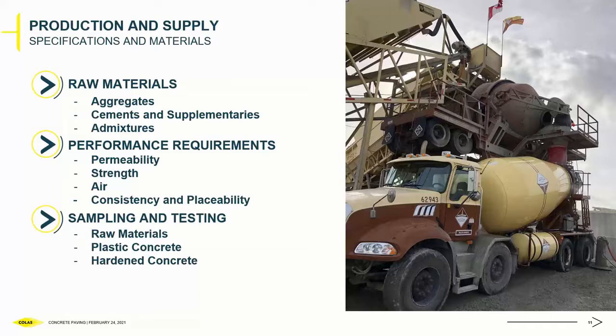And that also requires the supplementary cementing materials, like I mentioned, usually 25 to 30% replacement with slag. The air content is pretty straightforward. Minimum 3%, spacing factor of maximum 230, same as normal concrete. So there's nothing too exciting there.